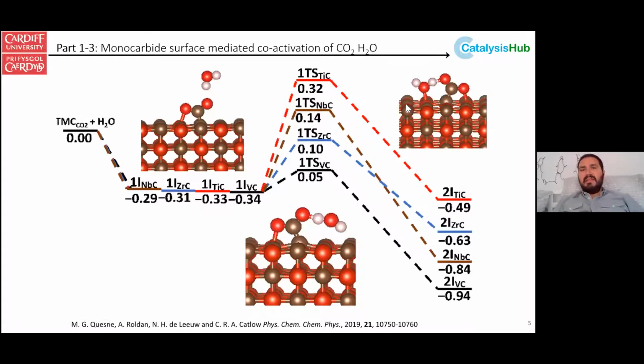We find there's a very different transition state energy. So with the vanadium, we've got 0.05 EV, and then we've got considerably higher for the titanium at 0.32 EV. But we tend to get quite a good correlation between the transition state energy and the exothermicity of the overall reaction. We find that the energy added for this co-adsorption is between 0.5 EV and 1 EV. So we have quite a strong extra energy associated with the co-binding, which could help this process happen on the dominant surface, which is the one that we would expect to be most, even if it's not most catalytically important, it's the most dominant in any nanoparticle.